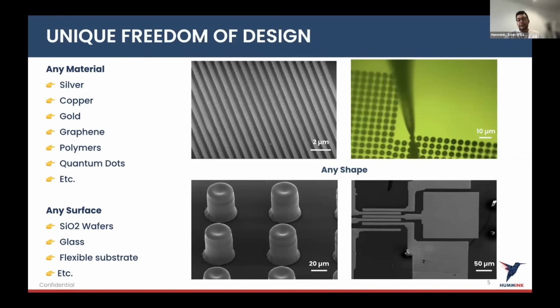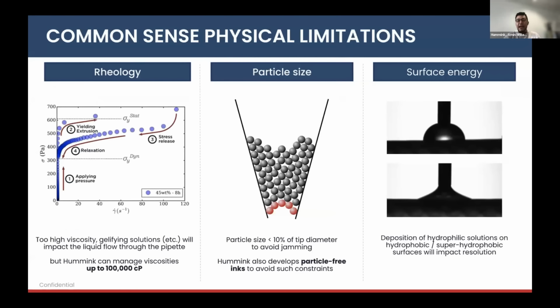You can also do some small structures in 3D with these bumps, very useful for advanced packaging applications. Waveguides that you can see on top left. The smallest waveguides period that we did is around 400 nanometers. You can make dots, and you can also make devices with very narrow gaps for increased electric field between the interdigitated electrodes. So we've been down to 300 nanometers or 200 nanometers for that. So huge electric field.